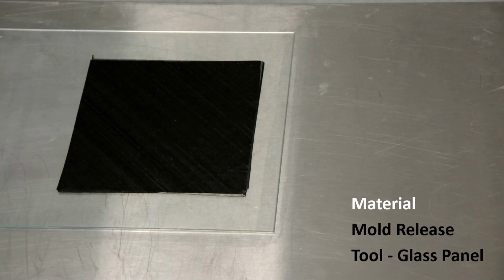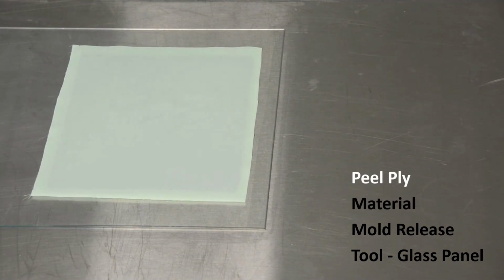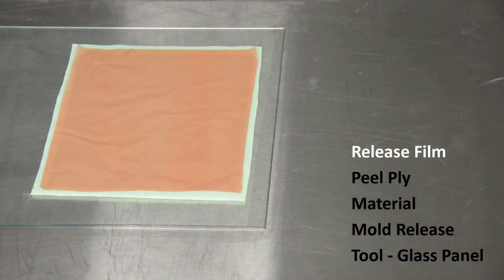After depositing our material, we will place peel ply on the laminate. This will produce a consistent surface finish good for bonding or painting while preventing consumables from adhering to the laminate. Peel ply also facilitates some evacuation of air and excess resin as it is a permeable fabric. We will place release film over the peel ply to prevent excess resin removal and to aid in removing the